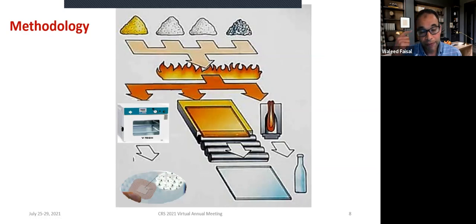So how do we produce it? It's simply a technology where you melt the medication at high temperature, and then when you have the melt, you fill your mold with the melted medication, cool it down, and then you collect your needles with an adhesive substrate.